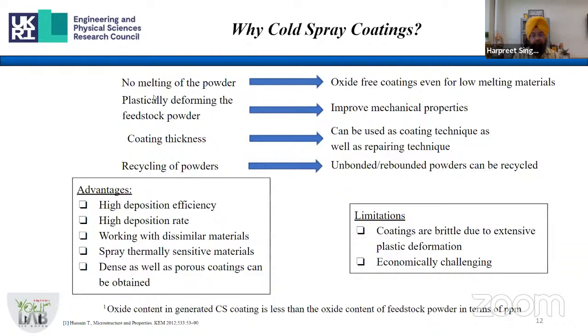It is heated in the process, but not well beyond its recrystallization point. It's like just warming the particles. So that means oxide formation will not be there, because those who work in coatings are always worried about these oxides which can form. And this challenge becomes greater when we have low melting materials or temperature sensitive materials. So in that domain, cold spray can be a very nice technology by which you will get oxide free